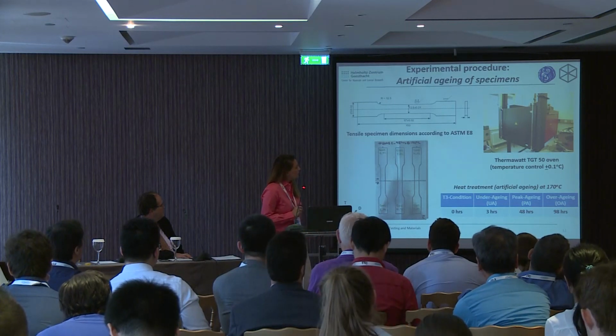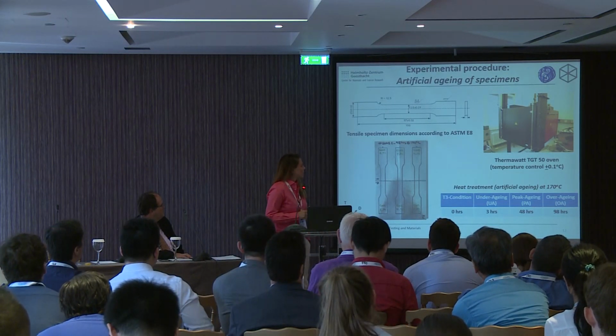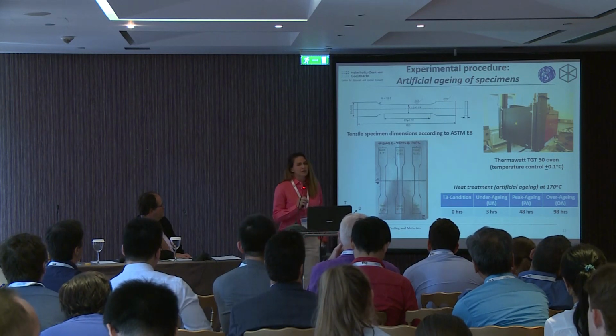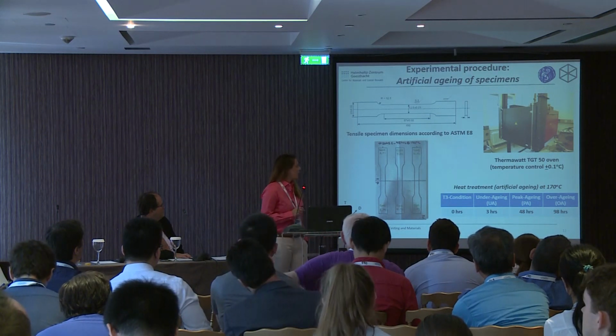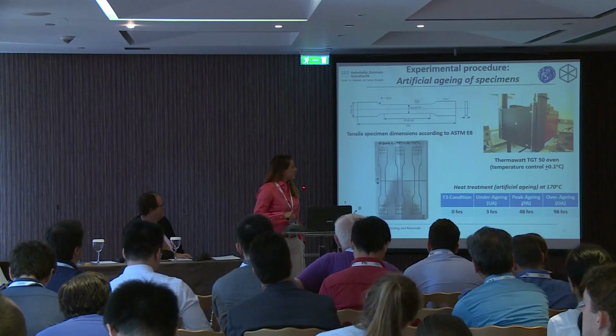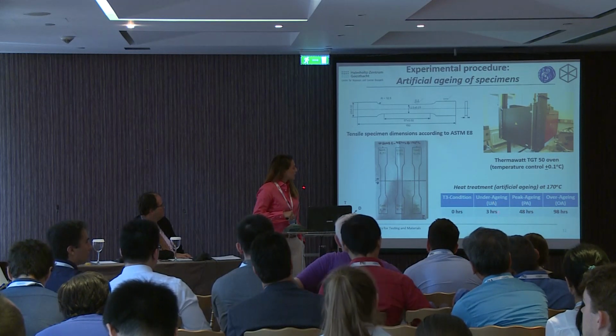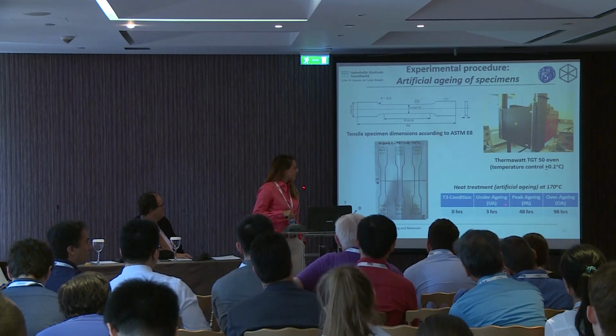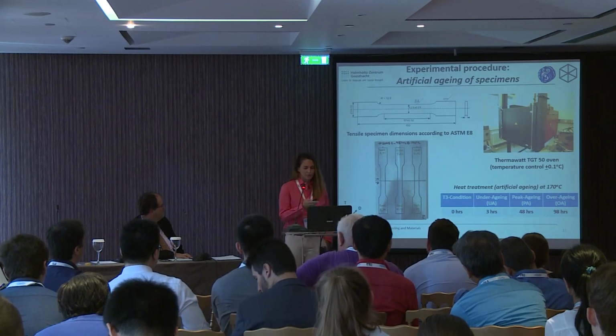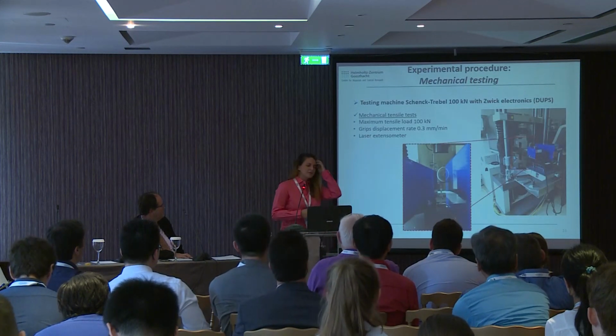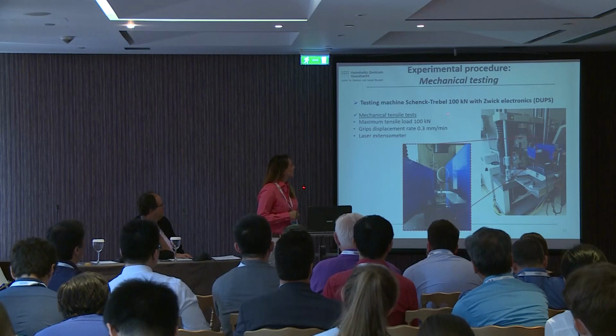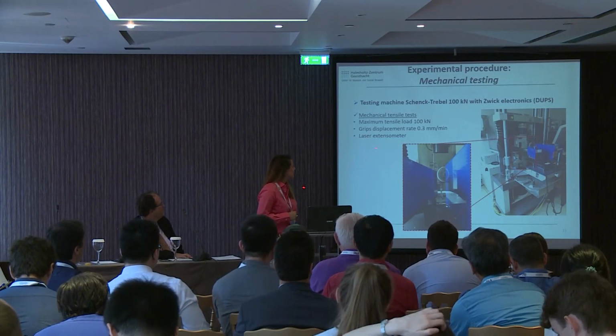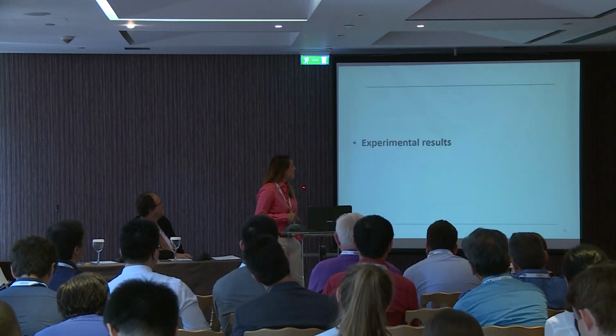This is the oven that we did the heat treatments in. The heat treatments were at 170 Celsius, and we chose 3 different times for the under-aging, peak aging, and over-aging conditions. This is a testing machine of 100 kilonewton, and we used a laser extensometer.